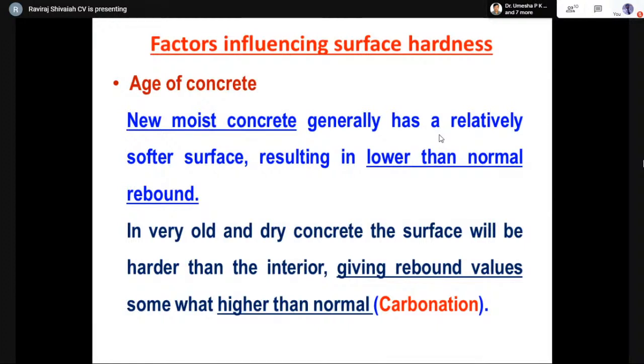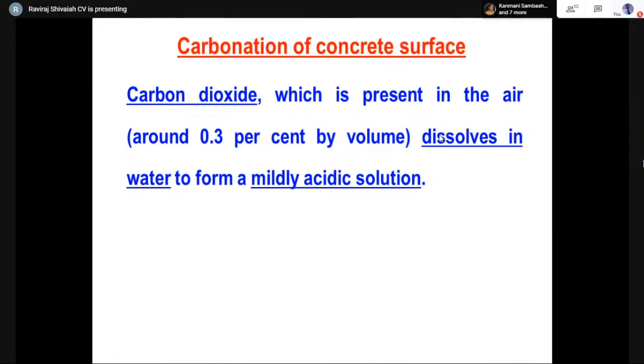And this is because of the effect of carbonation. Now I'm going to explain a very important phenomenon, carbonation, which happens in concrete structures. This is a very important thing that one has to understand. As you know, carbon dioxide is present in the air, about 0.3% by volume. This can dissolve in water, correct? Where is the water? It's in the pores present in the concrete at the surface. Once the carbon dioxide mixes with this water, it forms a mild acidic solution.